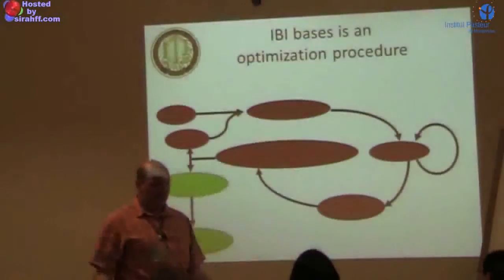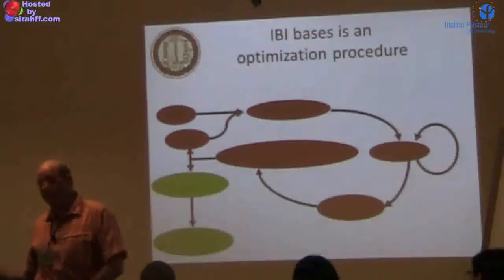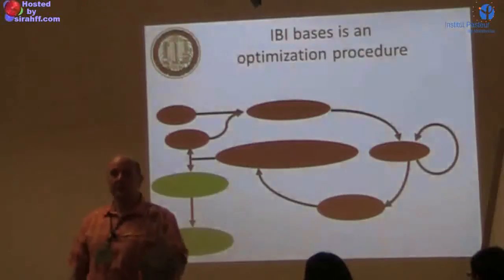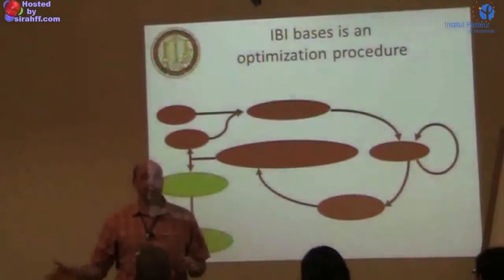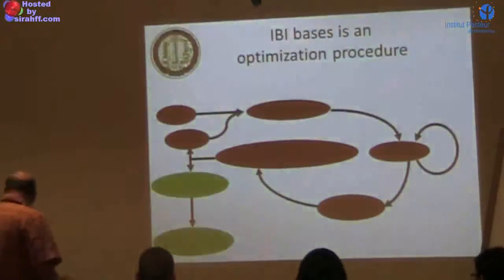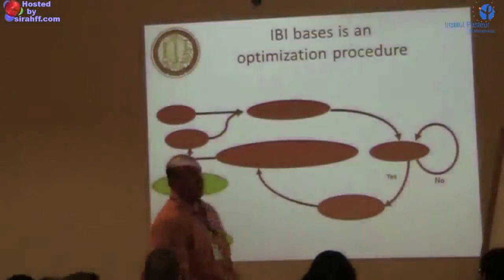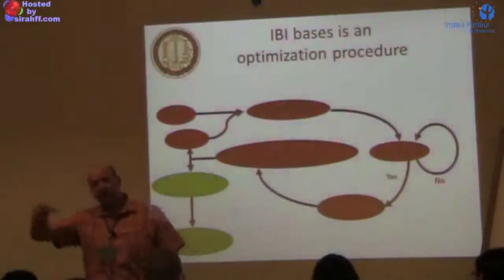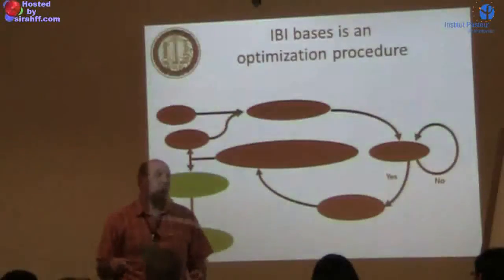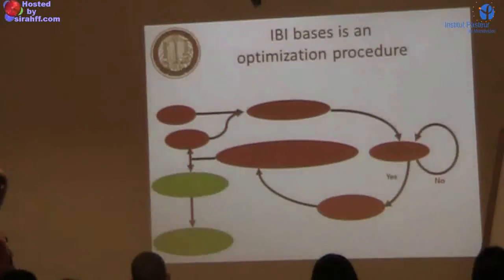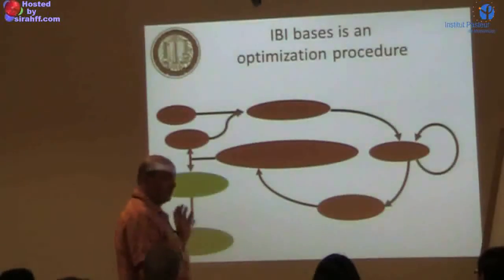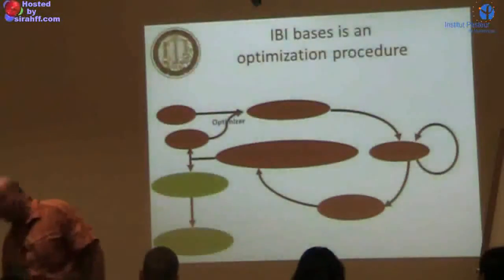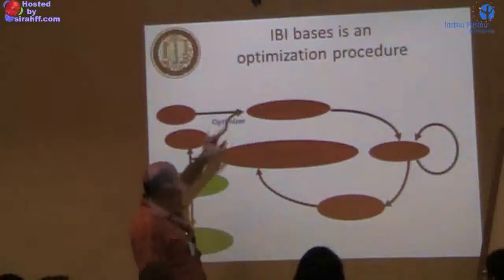This one I'll give you a first idea of how it works, and then we go into the detail of the different steps. Give some initial parameters. Ideally, if you want to do this all automatically, you have a tool which analyzes your system, finds out if everything is nicely equilibrated. If not, you run a simulation and you analyze the simulation. The next point, compare to the atomistic data. If you're not there, you have to use the optimizer. And the optimizer we are using is the IBI.